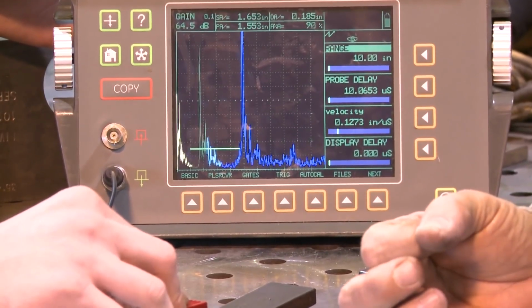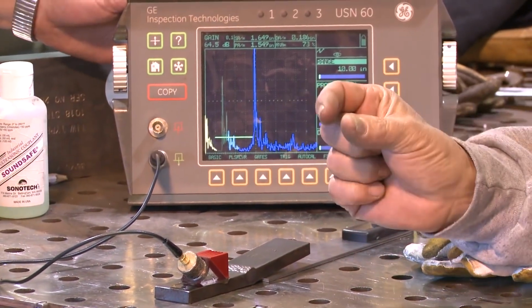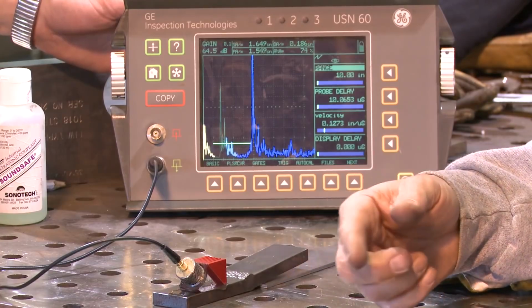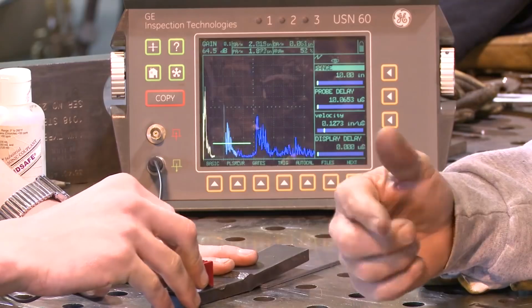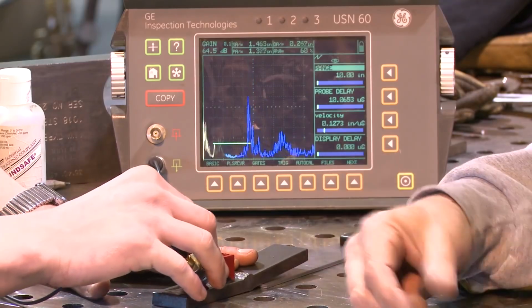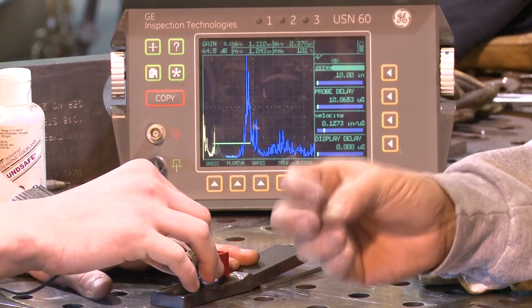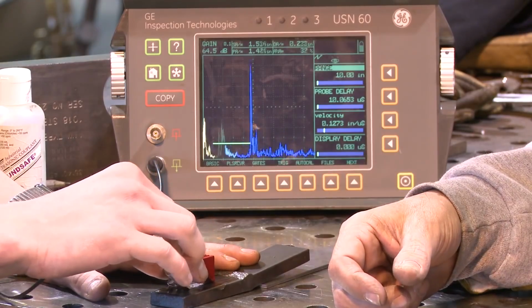So it's not necessarily porosity. This would indicate the stuff that I left behind, which were those nasty linear deposits of slag and glass. I think I've got a good reference to that here. I'll find it in the shop. We'll get some B-roll of that slag that we're talking about, the glassy brown deposits that are commonly left behind by gas metal arc welding. Man, this thing's loaded with stuff.